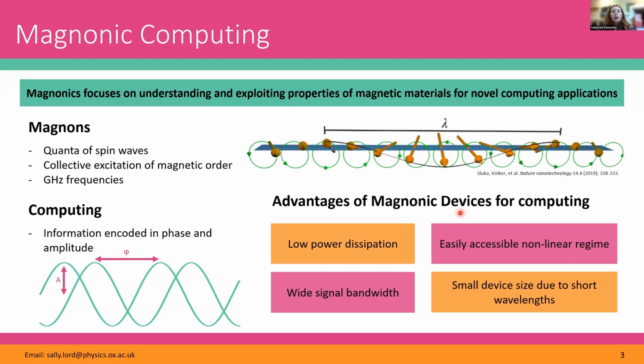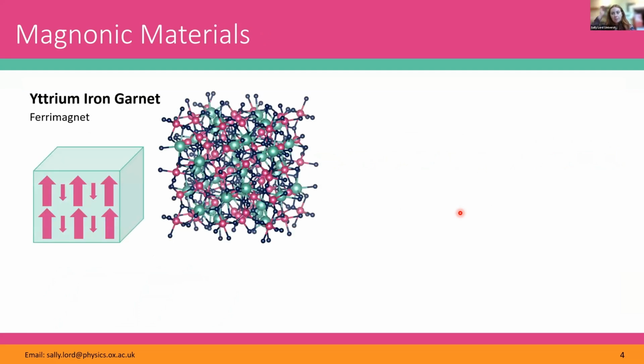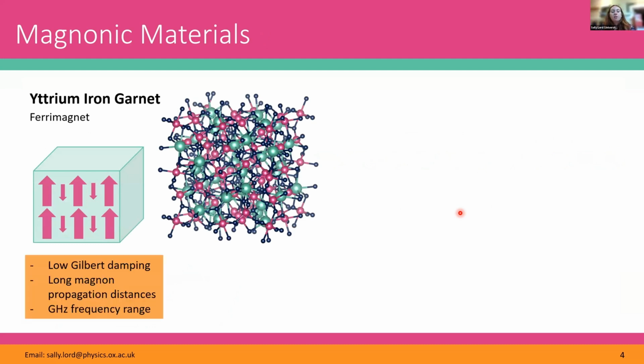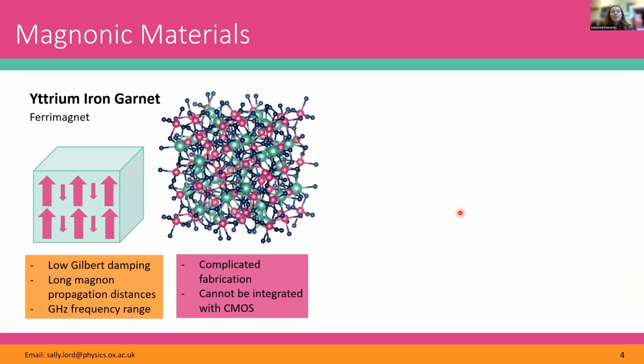But in order to develop Magnonic computing devices, we need to find materials that are suitable for these applications. So historically, most of the research has been focused on YIG, or yttrium iron garnet, because it has a really low Gilbert damping parameter and therefore long Magnon propagation distances. But there are some drawbacks to YIG, even though it appears to be the most ideal candidate. And these include the fact that it has a complicated fabrication process, and also as it's an insulator, it currently can't easily be integrated with CMOS, which reduces the commercial viability of YIG.